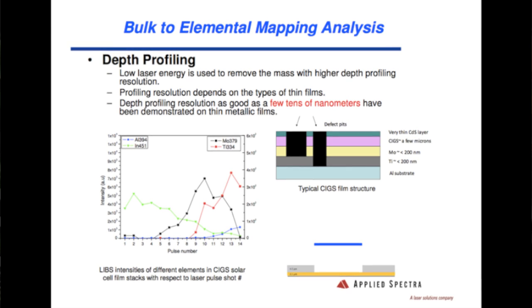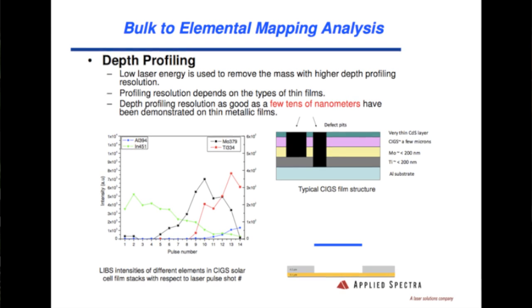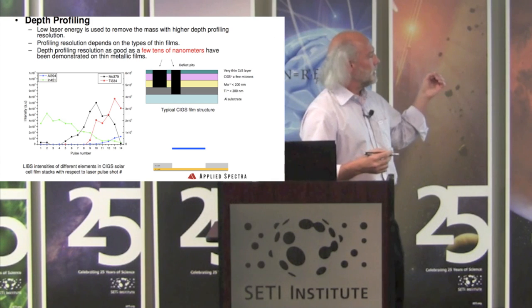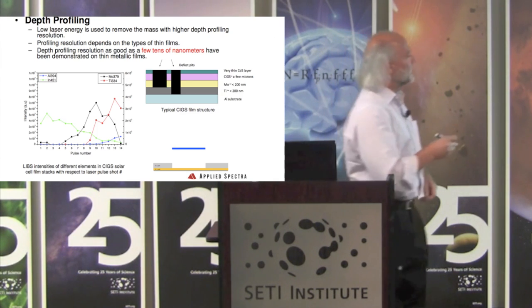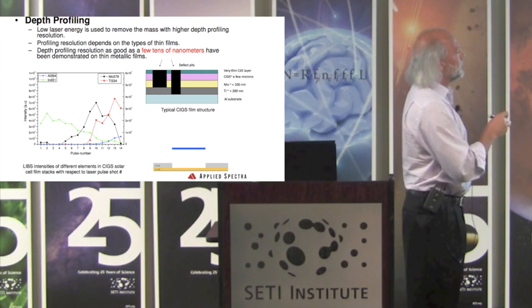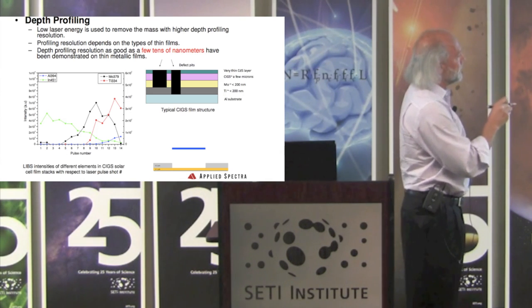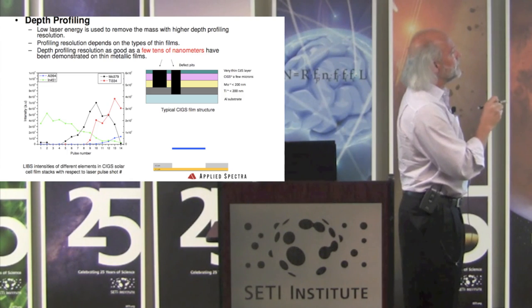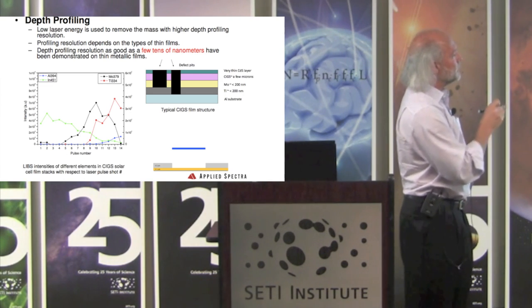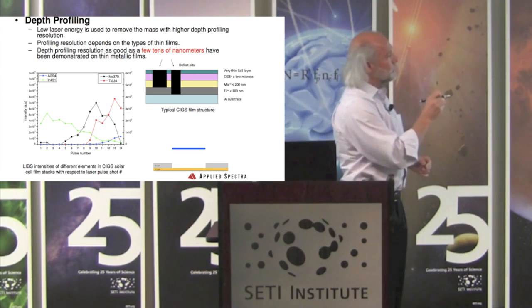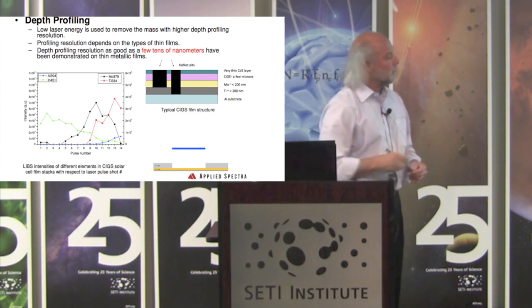Most people are familiar with secondary ion mass spec. You stick the sample in a vacuum chamber. We don't have to do this in a vacuum chamber. We can do this at atmospheric pressure. But again, you can look at all the different elements as you go through these different layers. And we're working on getting nanometer, tens of nanometer type depth resolution. And we're also working on getting nanometer spatial resolution.